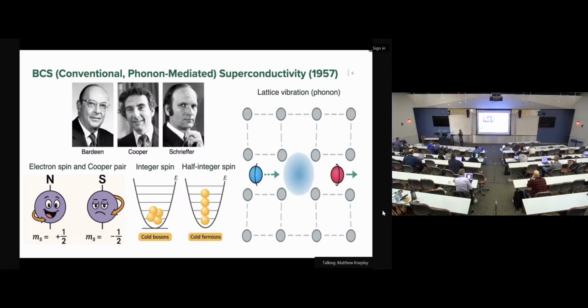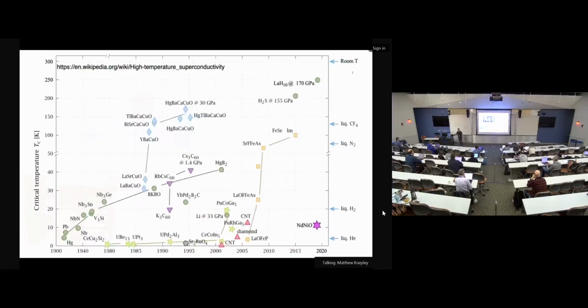So one possible way is through a lattice vibration, or what we call a phonon. The idea is that, for example, if I have one electron pass through the positively charged ionic lattice, then it will attract the lattice inwards, and after some time delay, the second electron comes in. It feels the attraction from the lattice, so effectively these two are bound together as a Cooper pair. So this is the mechanism of forming bound electrons to form superconductivity. But this explains only one family.